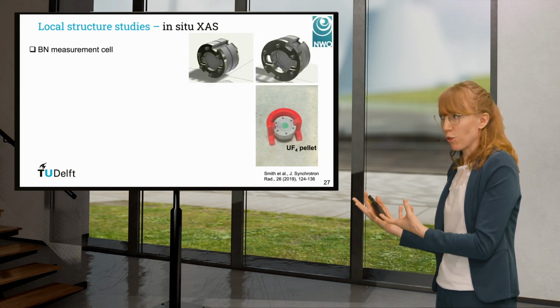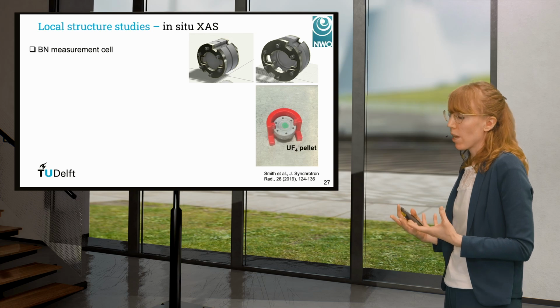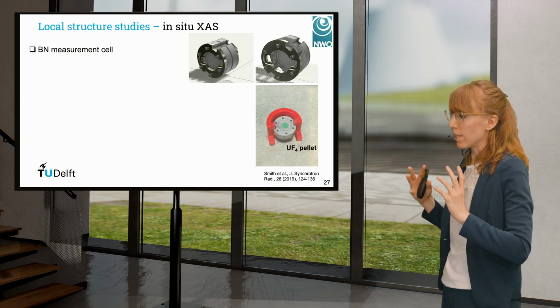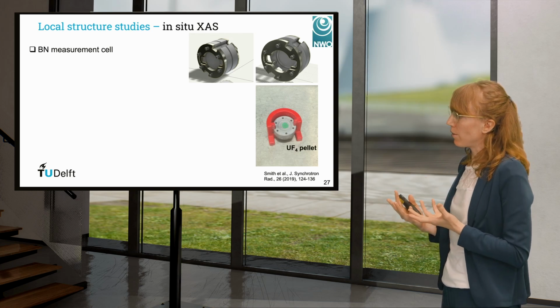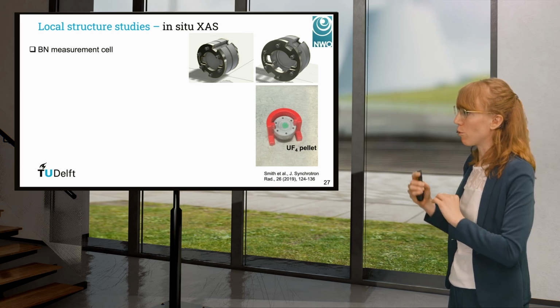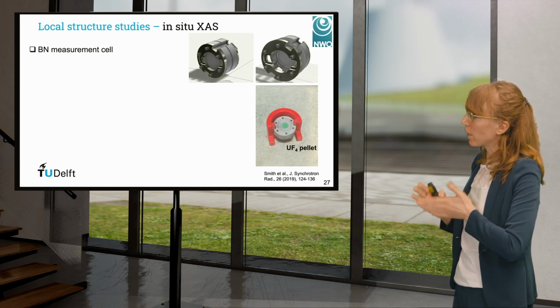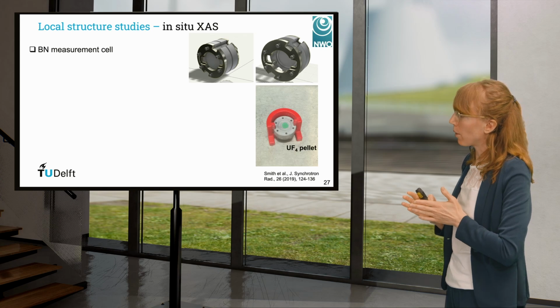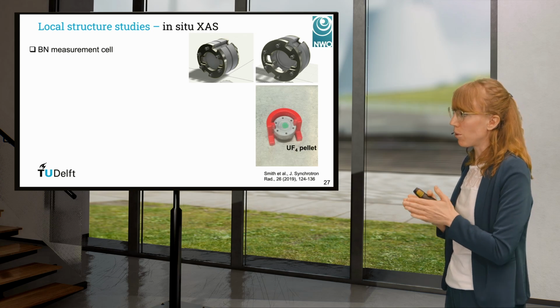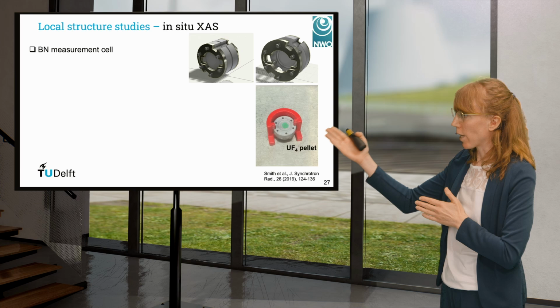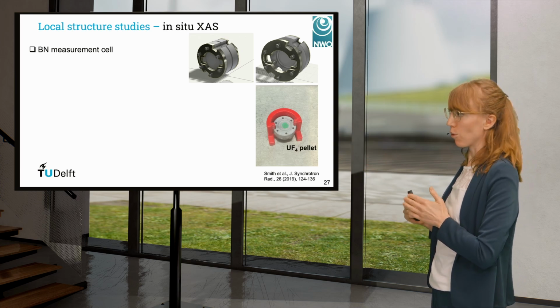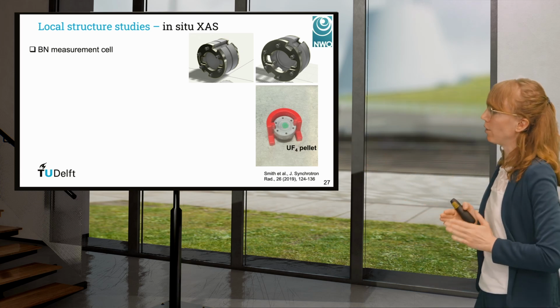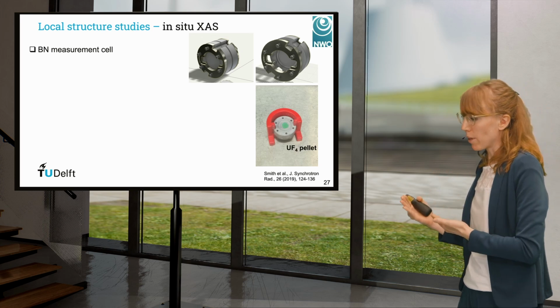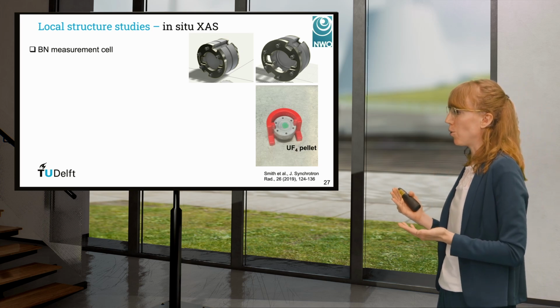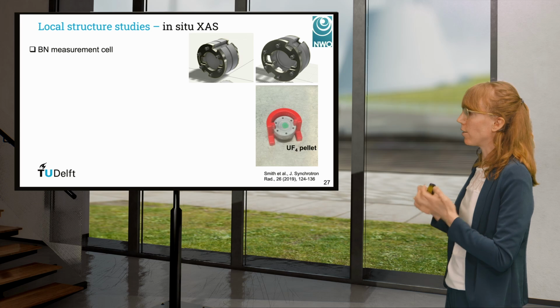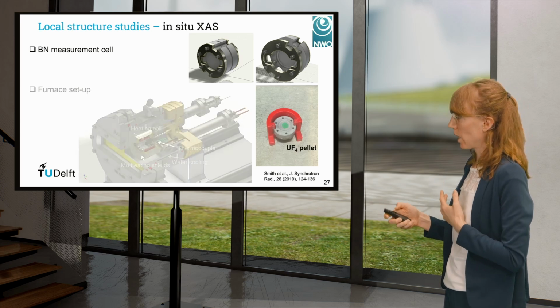To perform this kind of experiment, we had to build a setup. We had to design and build a specific measurement cell, which you can see on the picture. This cell is basically 2 boron nitride plates that encapsulate a sample. You can see a small pellet of that sample on the picture in between the plates. Boron nitride is one of the only materials we can use. It's transparent to the X-rays and does not react with the salt.